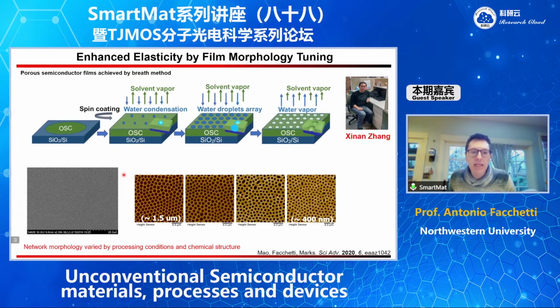So the question is, can we embed this type of morphology into organic semiconductors in a very effective manner? One way to create this type of morphology is by using what is called the breath figure method, which consists of spin coating the organic semiconductor film in an environment containing water, so a very high relative humidity. The process is such that you have water condensation during the spin coating, and these water droplets create cavities, which creates the porous morphology, okay? And by changing the water pressure, by changing the solvent, you can tune the porosity dimensions quite accurately.